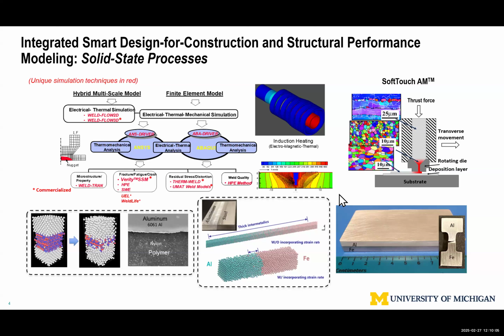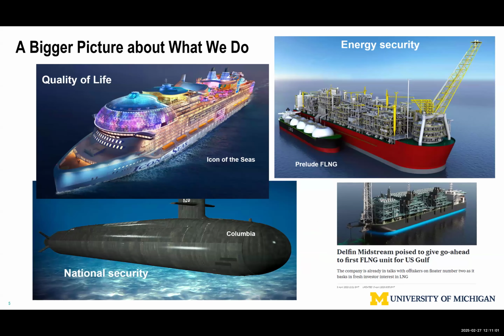One key thing here is the reason I mentioned some of the phenomena not being fully understood. For example, consider aluminum to steel. This is a classical problem people have been struggling with for the last 70 years, because they form intermetallics that are very brittle and can crack immediately after welding, after putting together. But if you induce a strain rate to such an extent that it produces a shear localization process that can become adiabatic and self-energizing, the strain rate effect significantly reduces, by two or three orders of magnitude, that transition zone between steel and aluminum alloy. This is what this chart tries to show. We can replicate that in our experimental setting and demonstrate that the sample is very strong and also corrosion resistant. Later I'll get into that a little bit. So those are the nitty-gritty details.